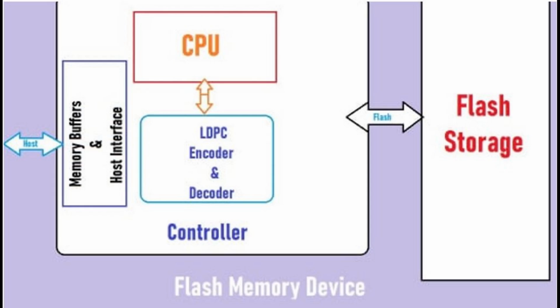Data sheets of Atmel flash-based 8-bit microcontrollers typically promise retention times of 20 years at 85 degrees Celsius (185 degrees Fahrenheit) and 100 years at 25 degrees Celsius (77 degrees Fahrenheit). The retention span varies among types and models of flash storage.